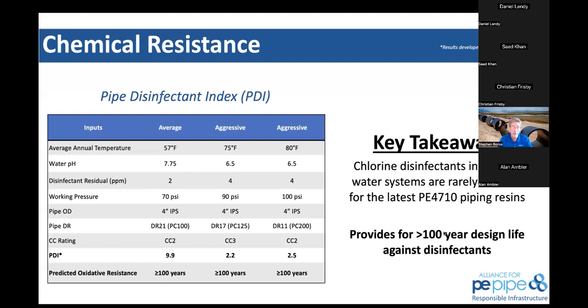You go to even the most aggressive one all the way on the right-hand side. Let's say you're in an area where you have 80 Fahrenheit average annual temperature of your water. That's pretty warm. The pH is really on the low side, 6.5. The residual chlorine is on the high side, 4 ppm. Working pressure rating, 100 psi. Even for 4-inch DR11 pipe, using the mid-class CC2 range polyethylene, with CC3 being the most resistant, even with that, you have well over 100-year design life of the product.